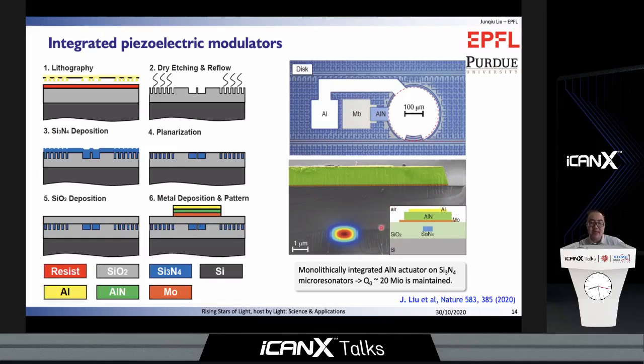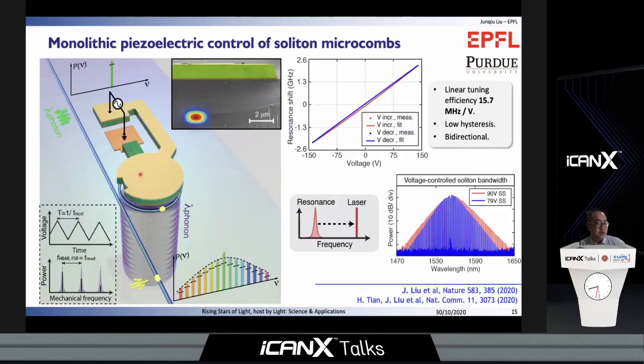As we use thick silicon dioxide between the optical waveguide and the metal, the high quality factor of 20 million is maintained. This is the key for soliton generation. This slide shows how the device looks. When applying an AC driving on the aluminum nitride, the stress-optical effect or bulk acoustic wave can be induced, which induces changes in the refractive index of the silicon nitride waveguide. This change in refractive index results in a modulation of the propagating light.